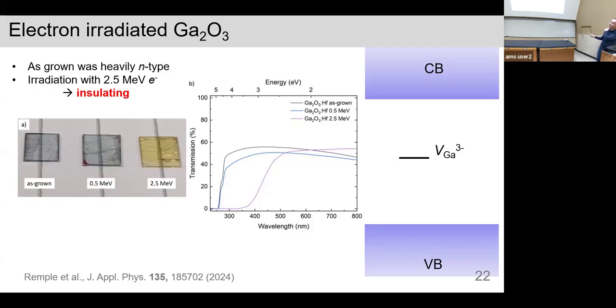And this is showing the transmission versus wavelength, and it's just verifying. So these two curves correspond to these two pictures, and pretty flat. But the last curve has this dip in transmission around 400 nanometers. So it's really like if you have an old white shirt that turns yellowish, it's because not enough of the blue is in there. And so this is the same thing. It's cutting out the blue, and so it gives it a yellowish color. The eye is a terrible spectrometer. I mean, lots of things look yellow, and then you look at the spectra and they're quite different.